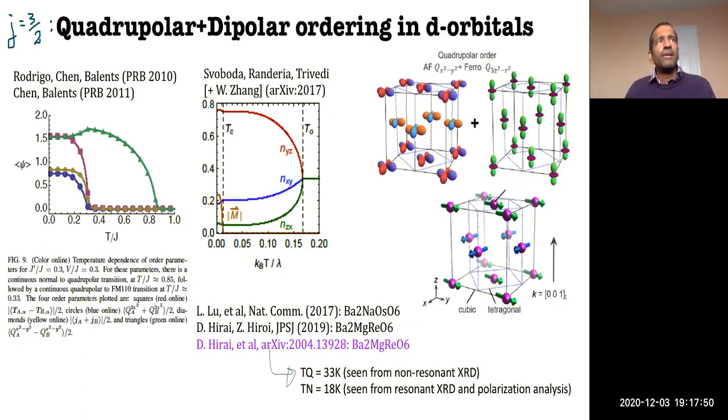Here, what we find from the analysis of the phonon modes that my student and I have been looking at is which types of low energy modes get affected. People have measured phonons up to about 70 millielectronvolts, and a lot of the phonon modes are not directly related to this eg order. The phonon modes at low energies are typically things like rotations, so you do expect the signature on those modes is more subtle.